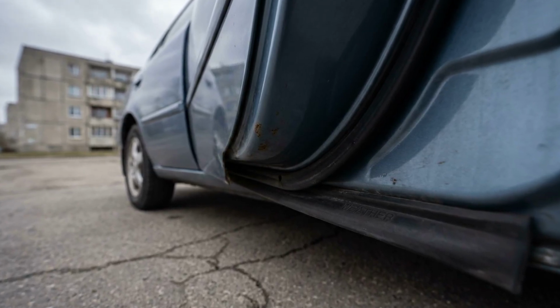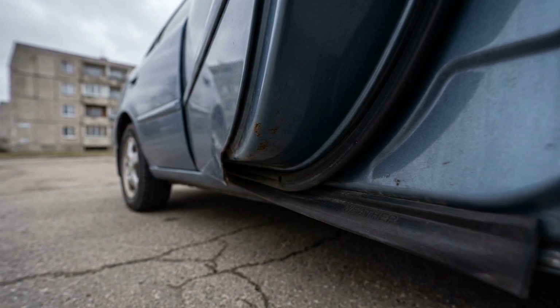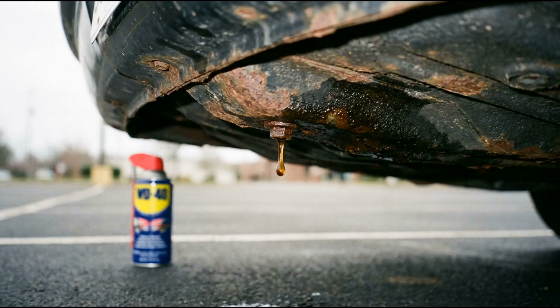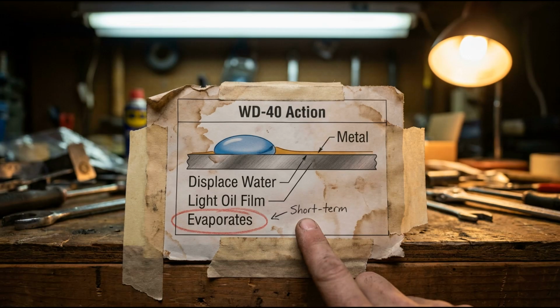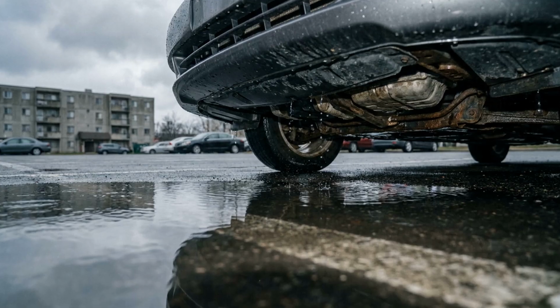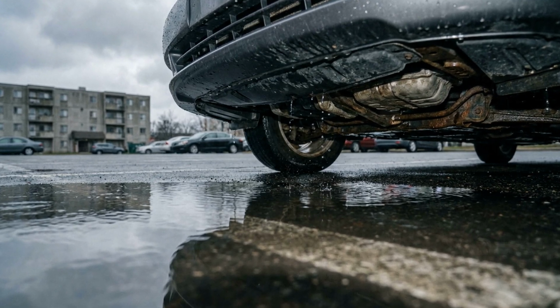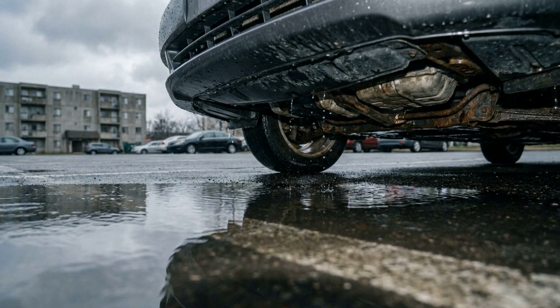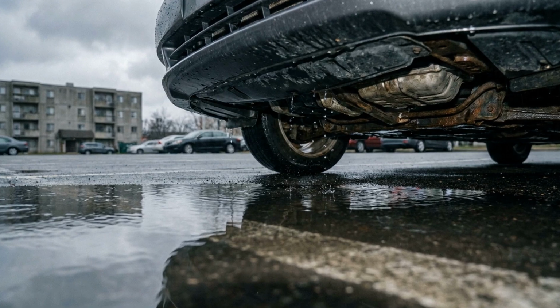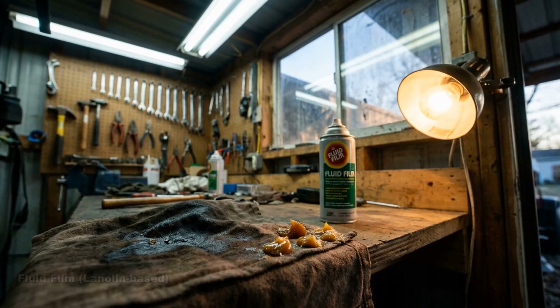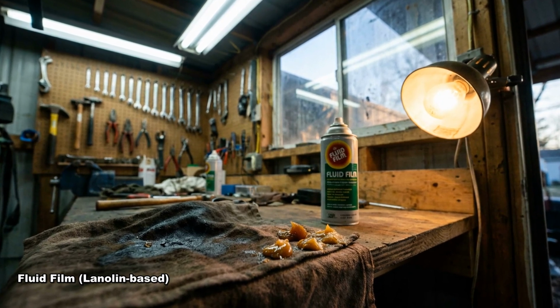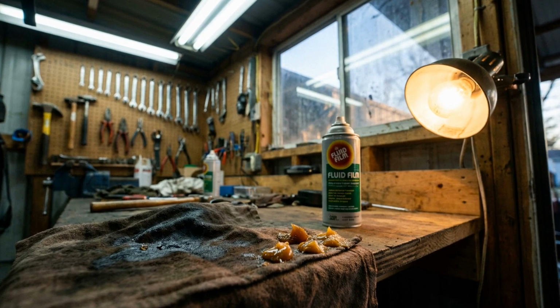WD-40 into hidden body cavities, inside rocker panels, inside door frames, along the underside of the trunk floor, as long-term rust prevention on older vehicles. Mixed. Short-term, WD-40 does displace water and put down a light oil film, but the film is designed to evaporate. Under a car in a real environment, road spray, temperature swings, humidity cycling, the WD-40 film is gone within a month. Long-term rust protection from an evaporating oil is not a real thing.